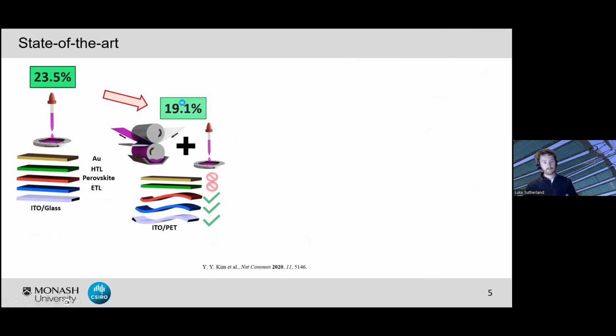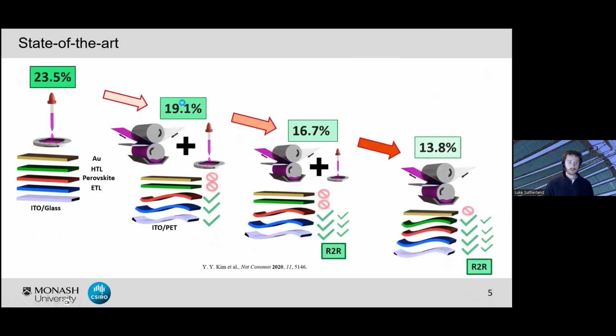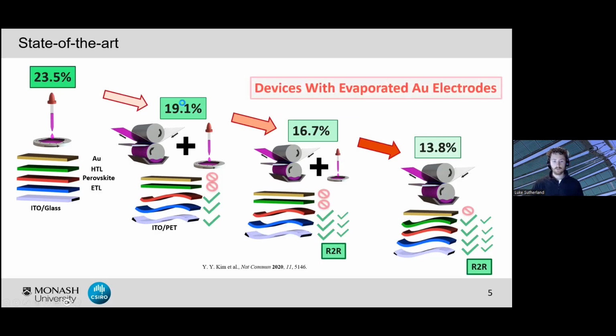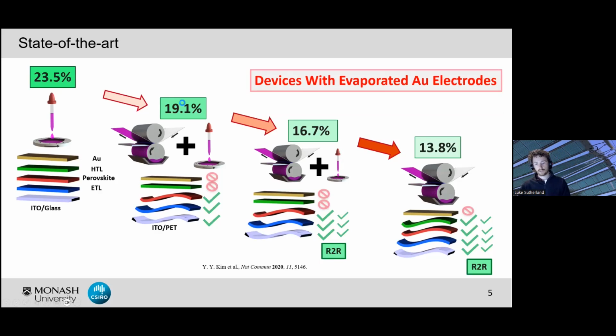So his team was able to fabricate really highly efficient devices, 23.5%. This was a few years ago now as well. This was based on ITO glass by spin coating each of our functional layers. However, then by introducing just simply the flexible substrate and the scalable coating process of gravure coating in this case, we see a significant reduction in the power conversion efficiency, all the way down to 13.8% in the end there by roll-to-roll printing each of the functional layers up to the hole transport layer. But as we can see in these devices, they were still all fabricated with evaporated gold electrodes.